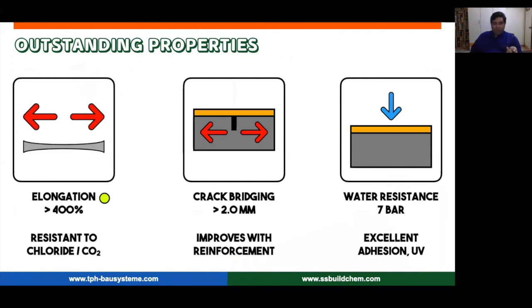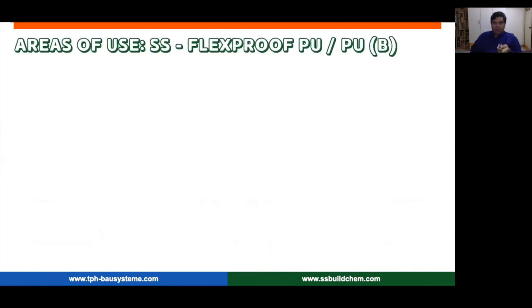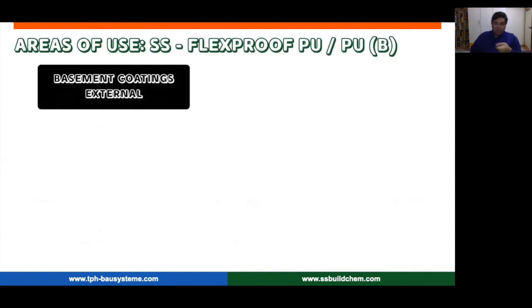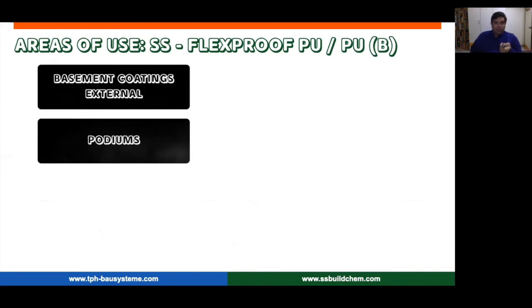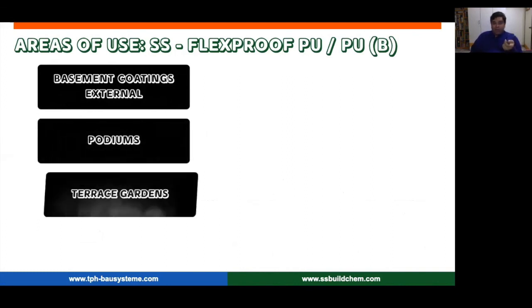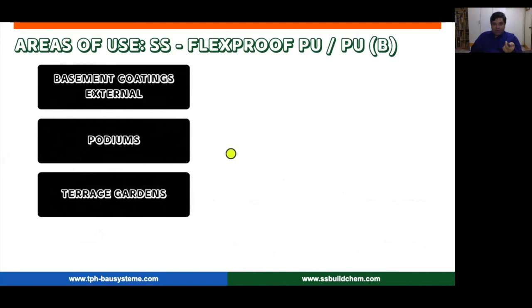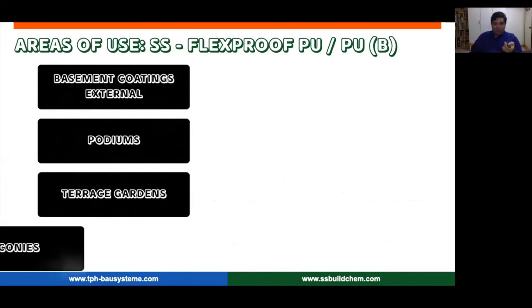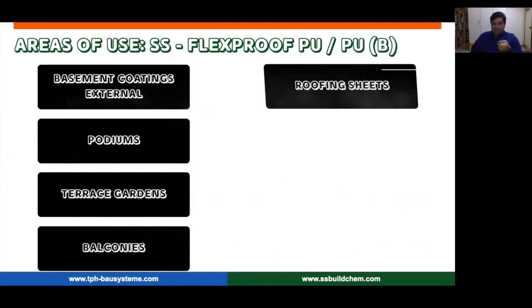So again, a few outstanding properties. The elongation is almost more than 400%, excellent crack bridging, very high resistance to water. You can always reinforce one of these coatings to get more performance out of it. And of course, it has good adhesion and the white one has good resistance to UV as well. So the primary areas where you use these materials are basement coatings on the external sides, in podiums, terrace gardens and balconies.